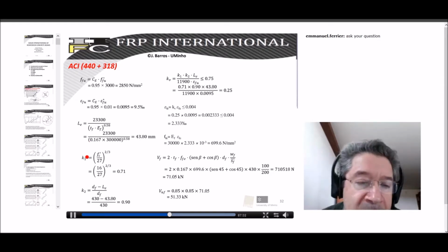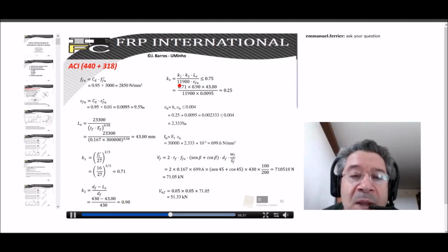So we need also to estimate the kappa 1 that depends on the properties of the concrete, and since the characteristic value of the concrete is 16 megapascal, we will obtain a value of 0.71. So depending on the type of shear strengthening arrangement that we are using, in this case U, we should use this equation to obtain the kappa 2. That depends on the df. df is the distance from the longitudinal reinforcement up to the top level of the FRP system, that in our case is 430 millimeter, and then we obtain the value of 0.9. So replacing here, we obtain for kappa V a value of 0.25.